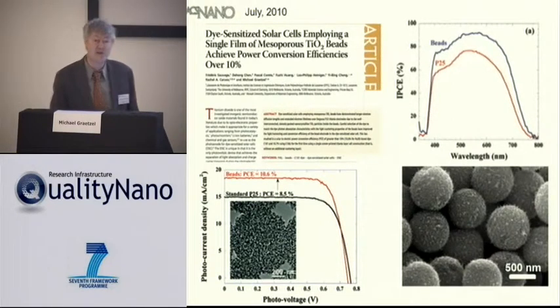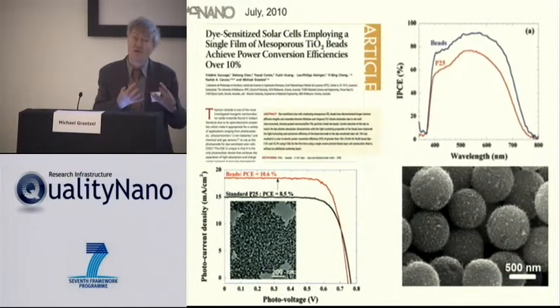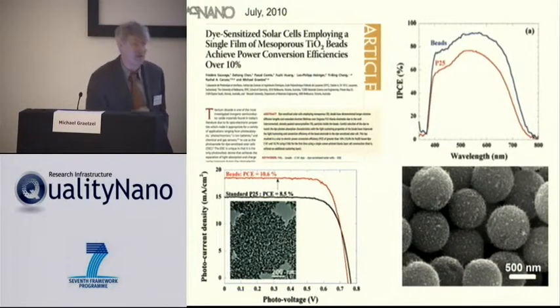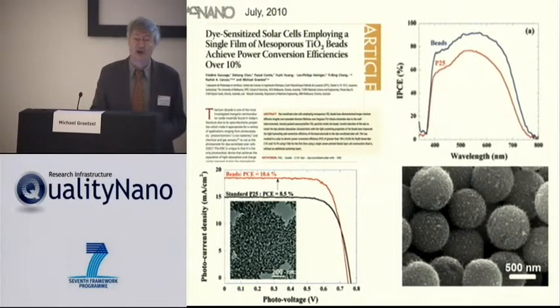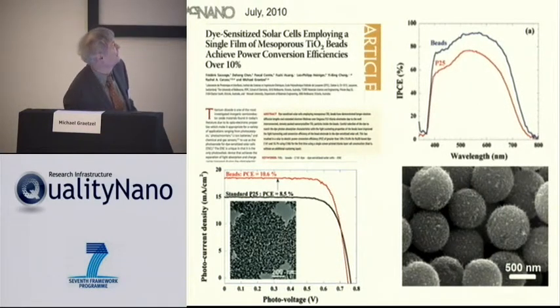So light hits those beads. They are, of course, loaded up with sensitizer. There will be a surge of electric power coming out of those beads. And for every photon that is hitting in the wavelength range of the absorption of the sensitizer, you get one electron back. You see over 80 or 90% conversion efficiency.